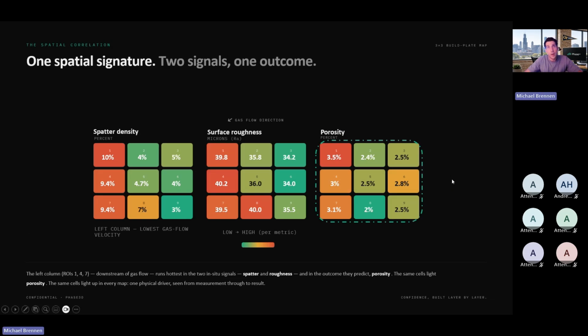The last thing that we wanted to look at was some sort of external ex-situ correlation that we could do in order to see if there was any correlation between the in-situ process variation that we were detecting and the final part results. So we did a basic Archimedes density test on the coupons in each of these regions of interest and took the average density across those parts. And again, what we found was this far left column continued to have worse performance, which correlated to the increased surface roughness and the increased spatter density.